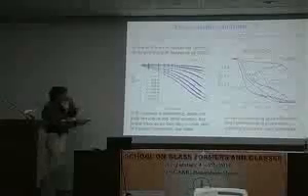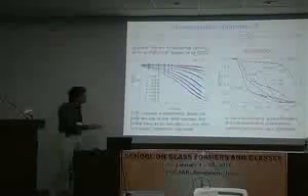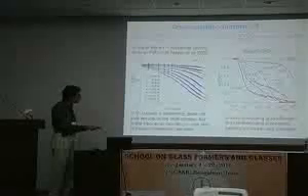That is to say, you see it directly that for large wave vector, the collective and the self become identical. And this trivial mathematical result you see directly here in the sodium silicate system. In red, it's the collective; in blue, it's the self. These are different wave vectors. This is a relatively large wave vector, and you see the two functions are indeed quite similar.